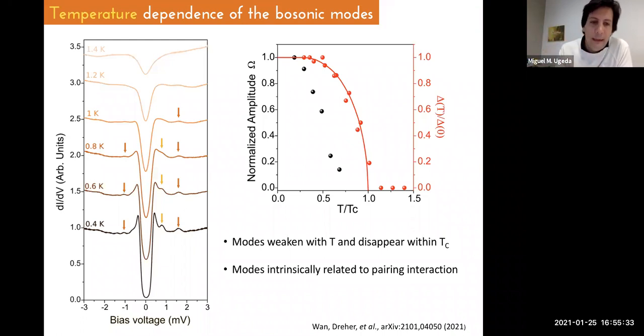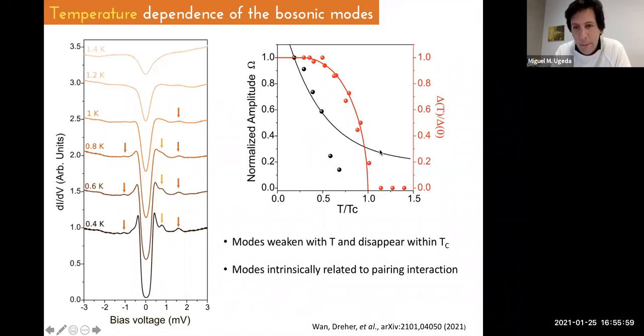But we have to rule out the possibility that these STS features are broadened by just thermal fluctuations. So here I show you the expected evolution of the amplitude with the thermal evolution. So it started here. If this broadening was just due to thermal effects, the evolution could be similar, but only halfway, because at some point the thermal broadening could allow us to see these features even above the critical temperature. And that's why we know that this decay is due to the weakening of the superconducting state. And we can conclude that these modes are intrinsically related to the pairing interaction or superconductivity.